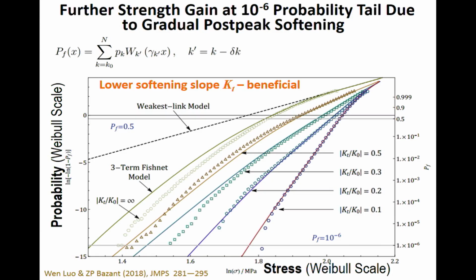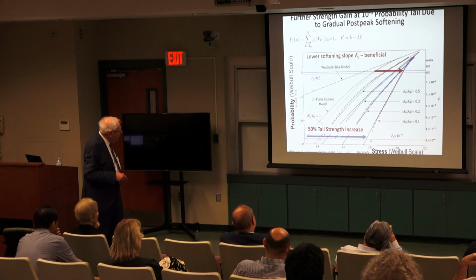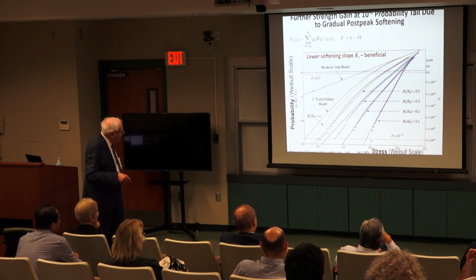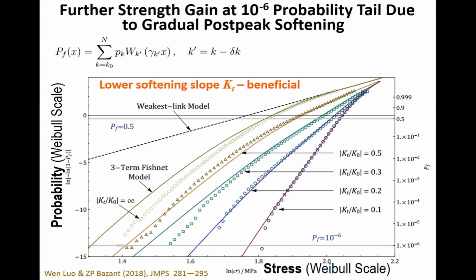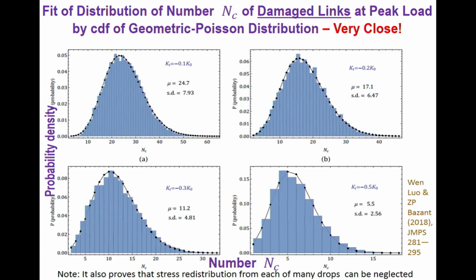And this is now verification by numerical simulations. Again, very extensive calculations, and they also give this kind of behavior. And you see the effect that there is a 50% tail strength increase at the probability line of 10 power minus 6. Again a very significant effect even for these fishnets which are progressively softening. And these are the fitted distributions. They are skew, of course.